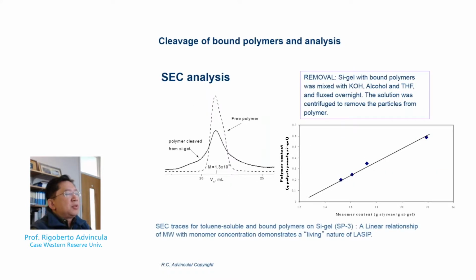What we will do in a typical procedure is to characterize the grafted polymer using SEC. So for example, if we use silica particle as a substrate, we will then mix it with potassium hydroxide alcohol to remove the bound polymer. The bound polymer can then be characterized normally by GPC. What we found on these procedures is that we were able to get a good correspondence of the monomer styrene feed ratio with the molecular weight of the polymer. Hence, we achieve here a type of living polymerization. However, not the exact monomer feed ratio, but in terms of the linearity of the process, it is well taken.